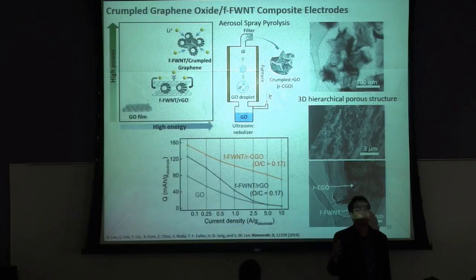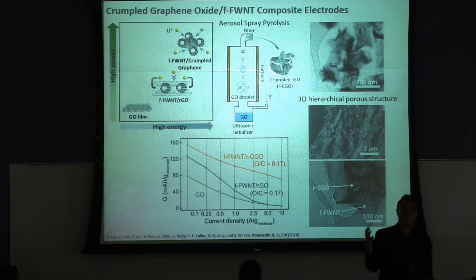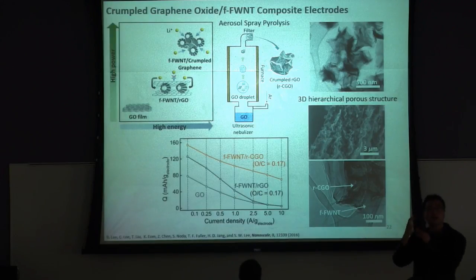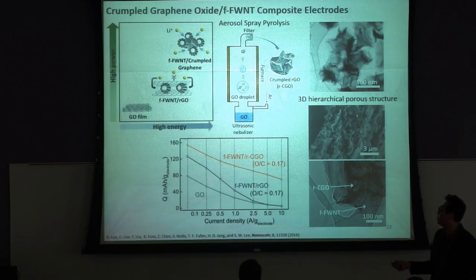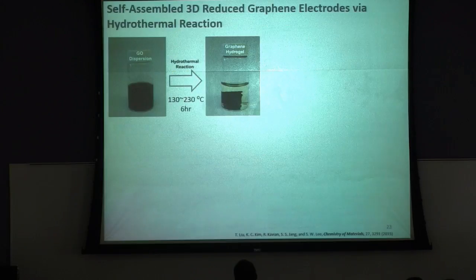The chemical structure is basically almost the same, but if we modify this microstructure, we can improve both the capacity and the rate performance of this kind of electrode. Okay, so next, let's remove the carbon nanotubes and try to design the electrode material based on only graphene.